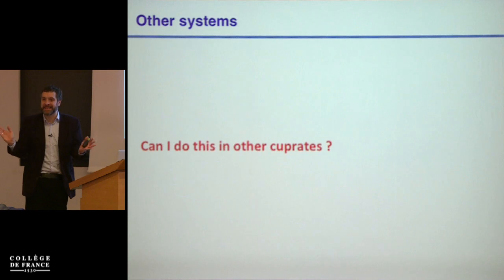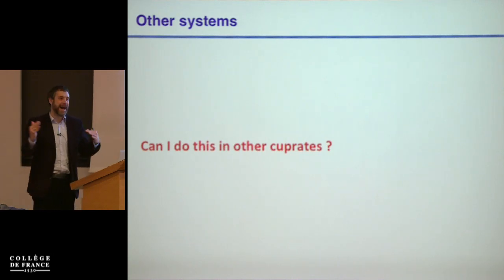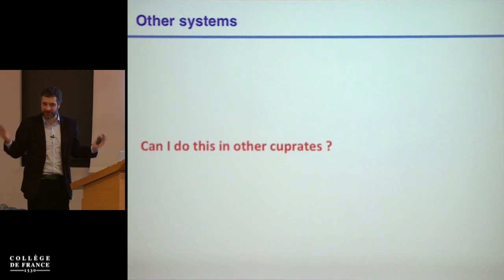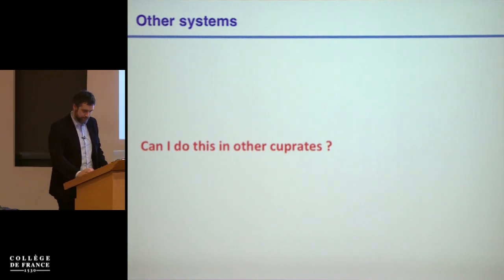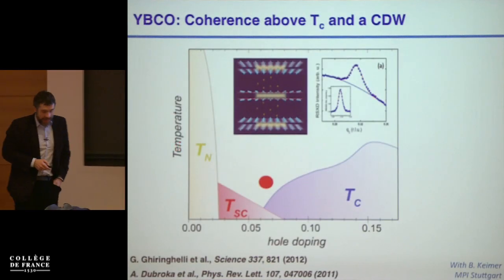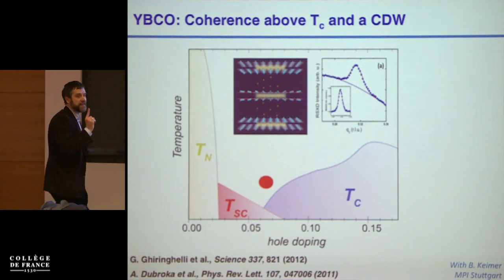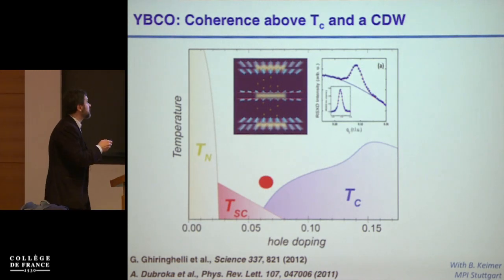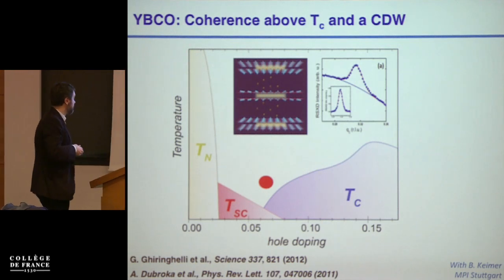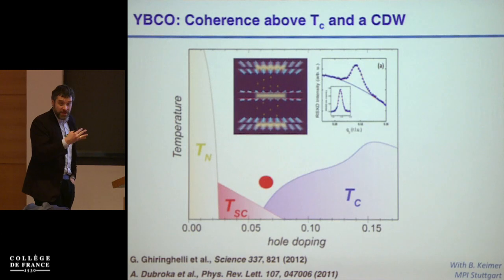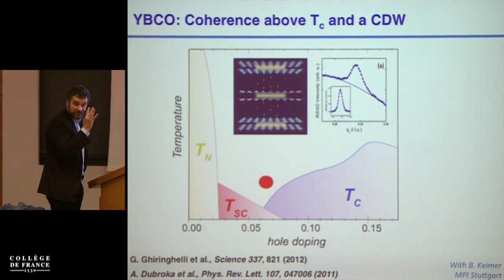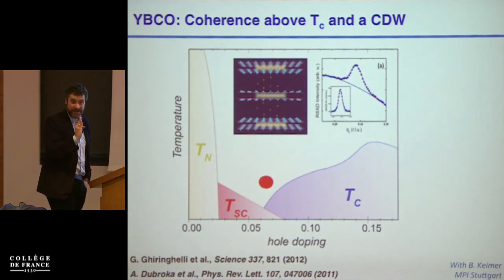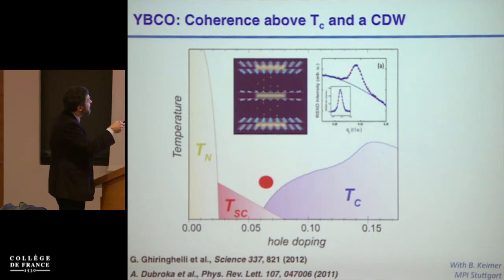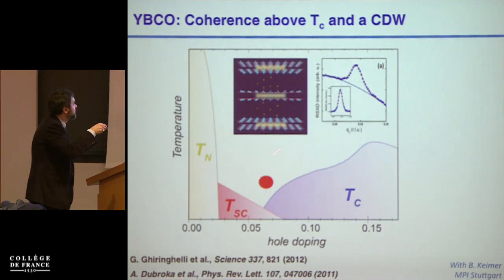And in principle, one doesn't need any fluctuating pair. One needs some stripe order that is either some sort of quasi-superconducting state or some enemy of a superconducting state. Okay? So let's see. You can take YBCO, and there are at least two things that happen in YBCO that have been discussed over the past few years. One, the flavor du jour, is the appearance of charge order peaks all the way to, say, 150 Kelvin in YBCO. For example, in YBCO 6.6, which is again close to 1/8 doping, one observes the appearance of a peak in the soft X-ray diffraction that is indicative of charge order all the way to, say, 150 Kelvin.